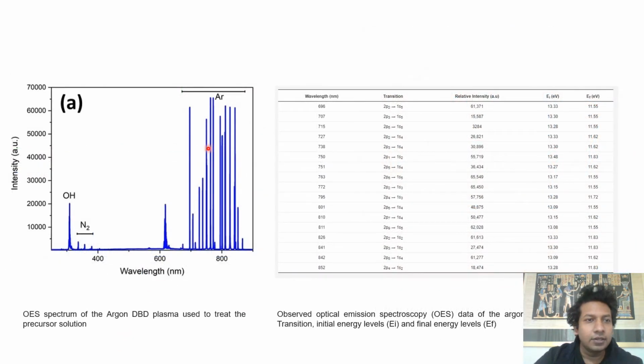This is an OES spectrum of argon DBD plasma. The emission spectrum of the plasma is primarily dominated by these argon bands. The hydroxyl band can also be seen here, which would originate from the dissociation of water. The second positive system of nitrogen can also be seen here in low intensity. Also, oxygen lines are located here and here, blended with argon lines at 777 and 844 nanometers.